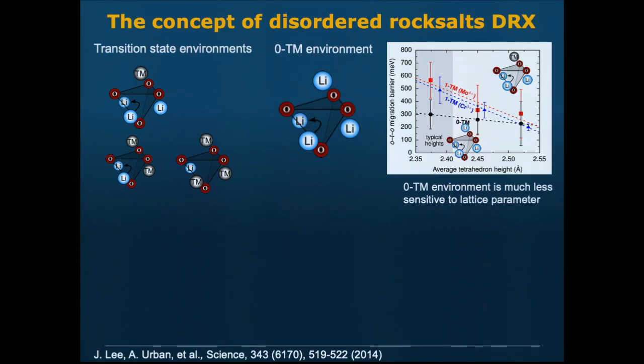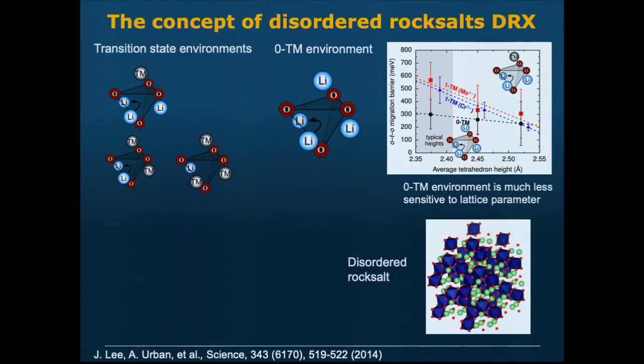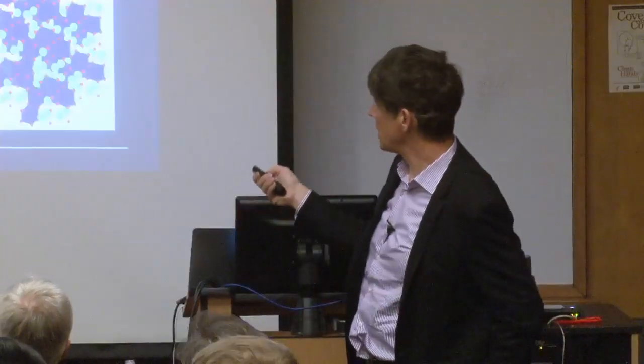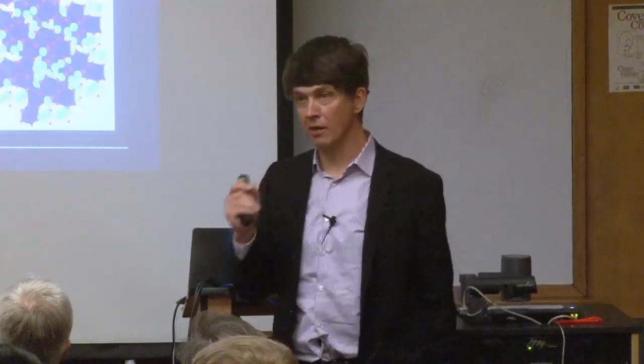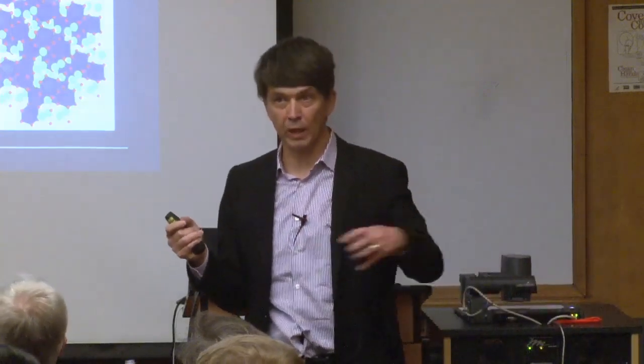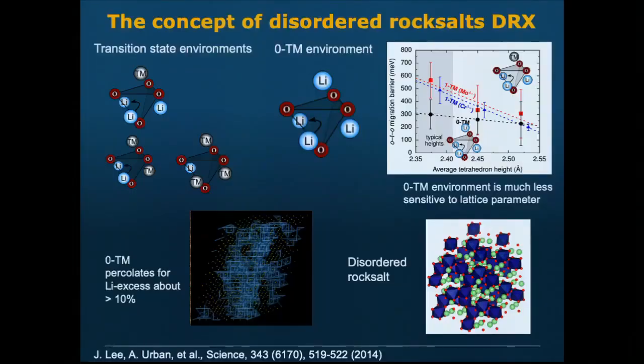Well, if you have ordered structures, in these layered structures, there are only 2 environments, this one and this one. And this one is the one you use. But if you were to disorder the material, if you were to start randomizing the cations, then you would statistically create all kinds of environments, right? And if you can make enough of these, you can actually get diffusion. So what we thought of is, can you make disordered rock salt? So they're still crystalline materials, but the cations are now disordered, so that statistically I get some of these. And then can I make enough of them that they percolate? Because I need diffusion throughout the whole crystal, so I need what's called percolation of these environments. And it turns out that you can percolate if you put about 10% lithium excess in.